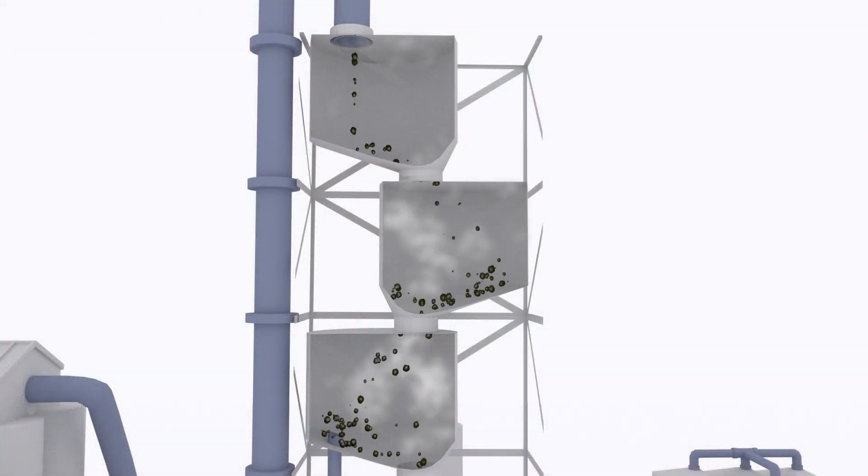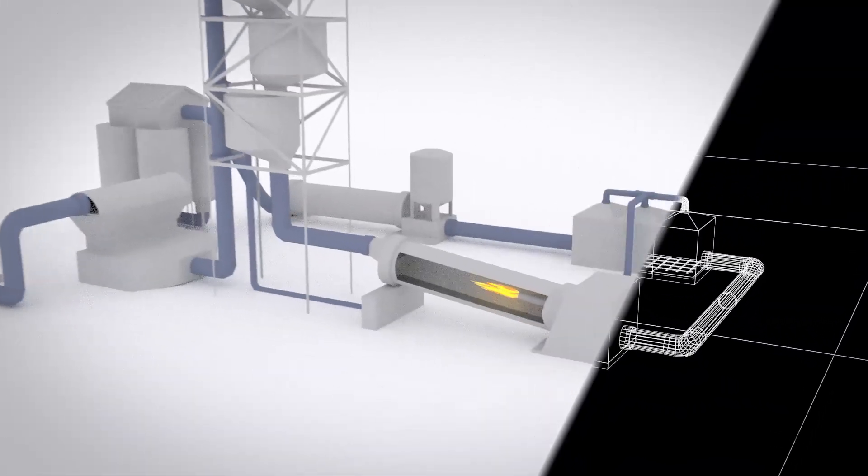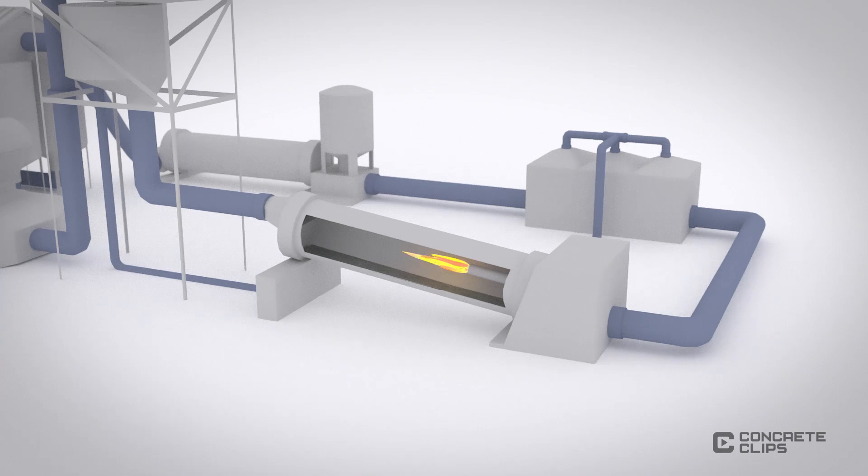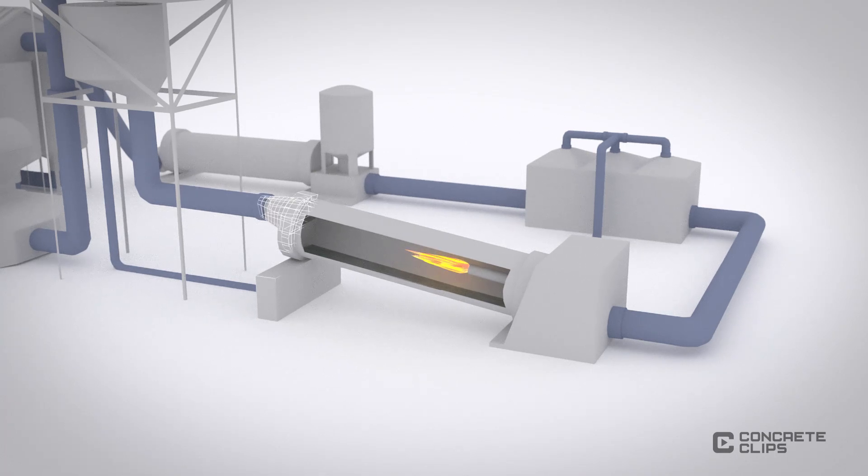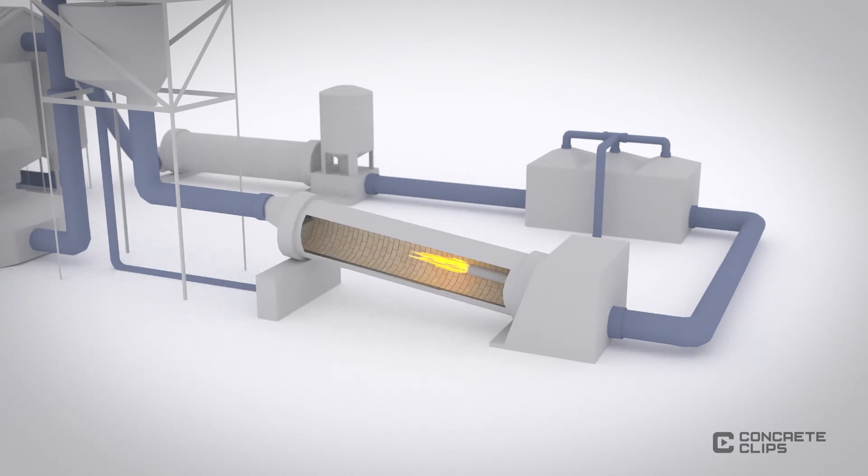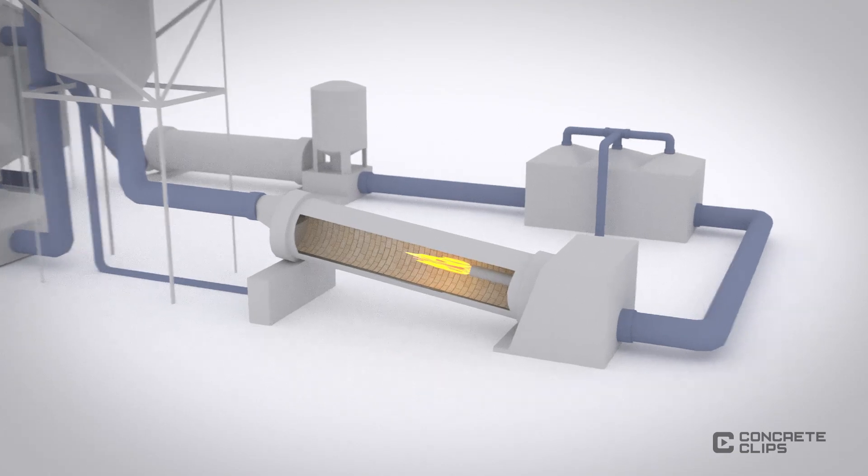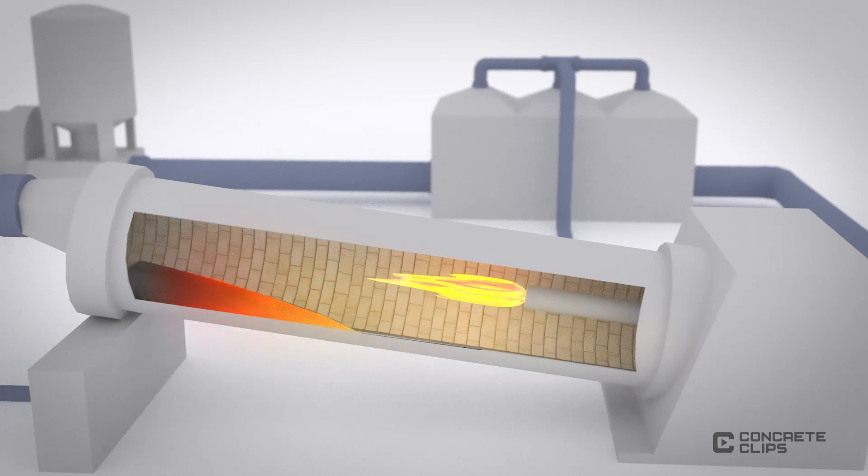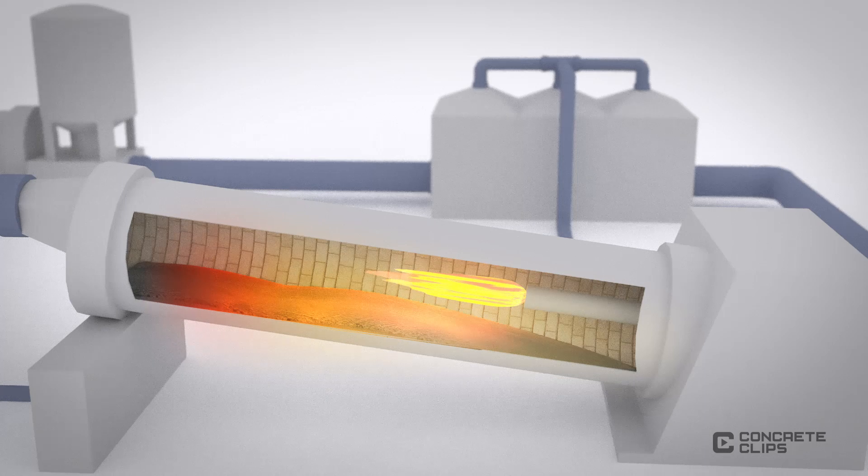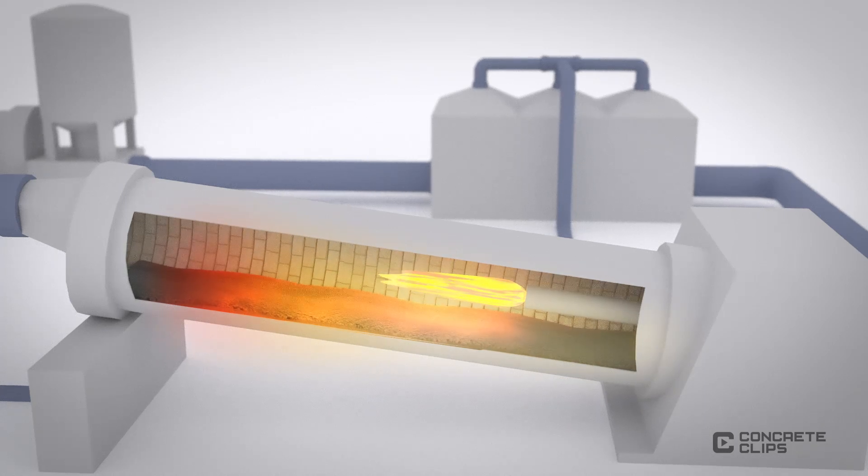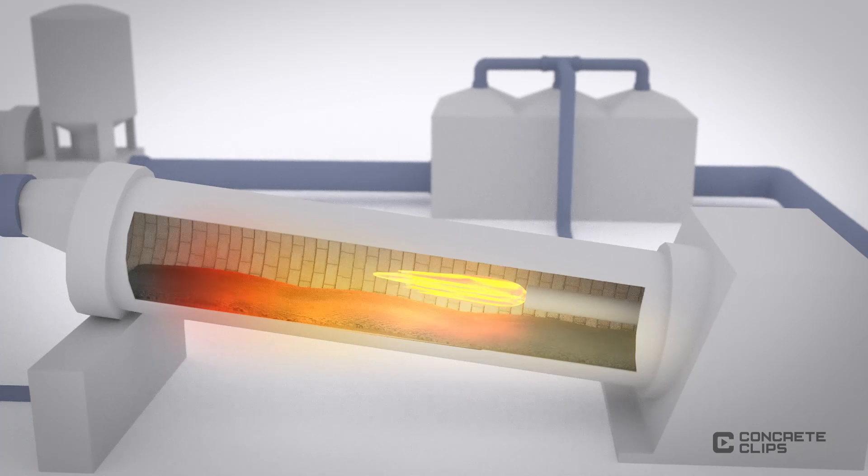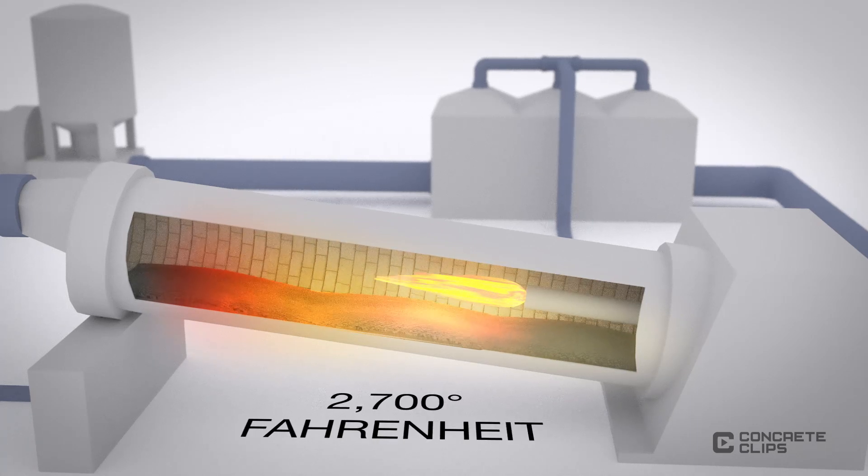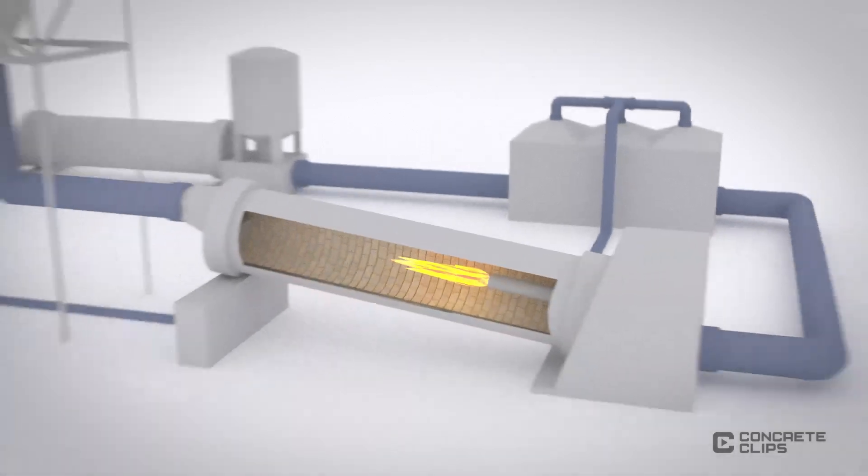This kiln is where all the magic happens. The vast majority of cement manufacturing today is done in a rotary kiln which consists of a large cylindrical steel tube lined with fire brick. The tube slopes slightly and rotates on its axis at a rate of 1 to 4 revolutions per minute. Raw mix is fed at the higher end and the rotation and tilt of the kiln gradually moves the material downhill towards the flame at the lower end and succumbs the material to gradually increasing temperatures as high as 2,700 degrees Fahrenheit.